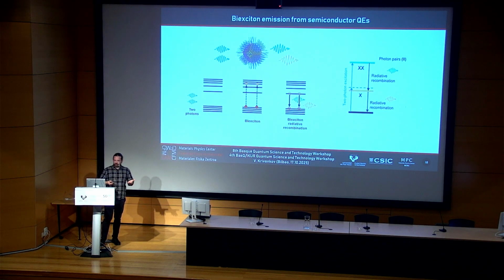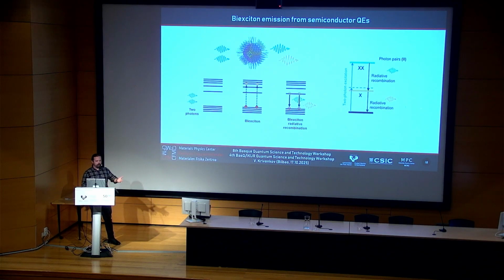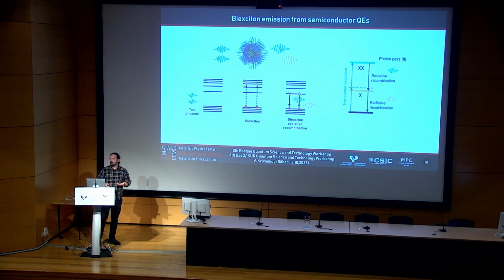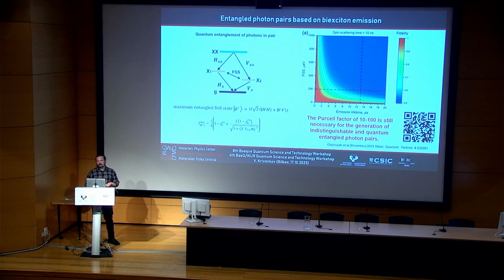But we also faced another important feature in the quantum dots we were coupling, which is related to the possibility of producing photon pairs from a single quantum dot. Indeed, if we realize two-photon absorption by the quantum dot, then we produce a quasi-particle, the so-called biexciton, consisting of 2 electrons and 2 holes in the same nanocrystal. And this can recombine with emission of 2 photons through the intermediate exciton level, from the biexciton state to the exciton state to the ground state, producing a photon pair. And if these 2 photons come from the same quantum states, they can be quantum entangled.